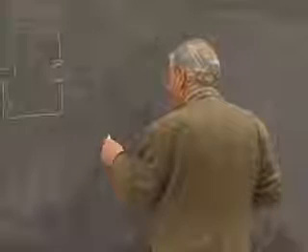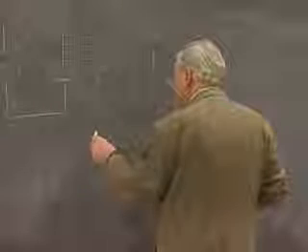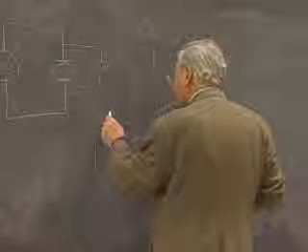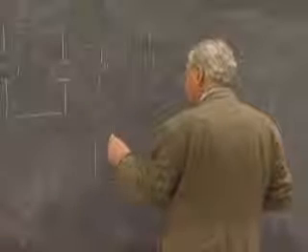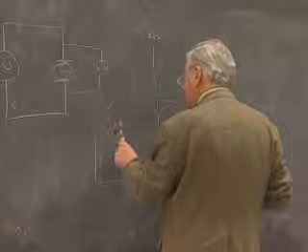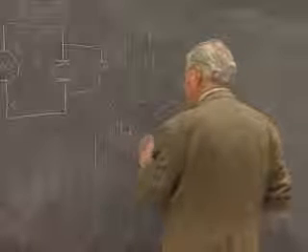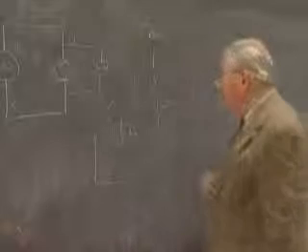Or alternatively, you could put this on a cathode ray tube and just have a sweep frequency and put the voltage across the electrodes on the oscilloscope screen, and you would see something like this, and then this discontinuity, and then maybe a second harmonic. And it would work just fine.